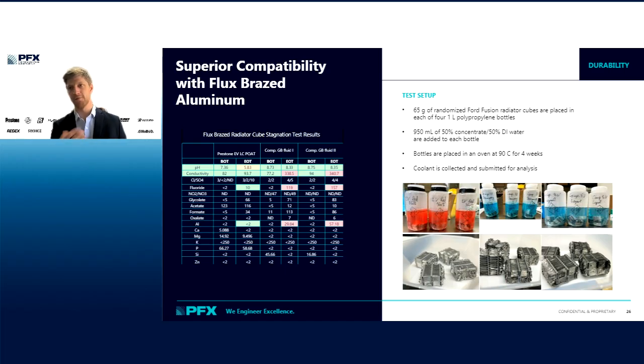They use a paste called flux. It's heavy in aluminum and fluoride, and it bonds these two aluminum metals together. And so this can be an issue. In the past, certain coolants have struggled to have compatibility. It can lead to deposits and clogging and overheating of components and potentially leaks.